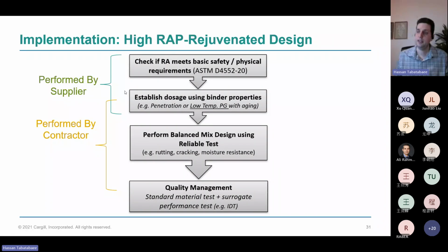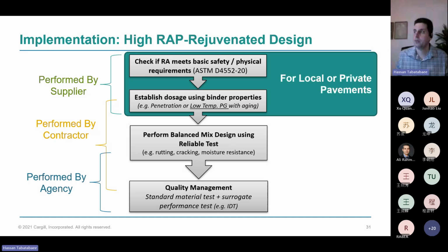After that, it's determining the design, which is confirmed using a performance-based design. Usually that is a normal design with some performance testing checks using locally accepted performance tests. And quality management is generally not going to change very much from what's normally done. There may be a higher frequency of RAP burn tests where you do the gradation and binder determination. Generally, for local or private pavements in North America, the first two steps are the only ones that are really done.